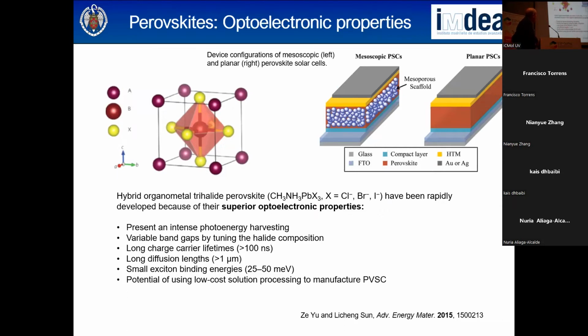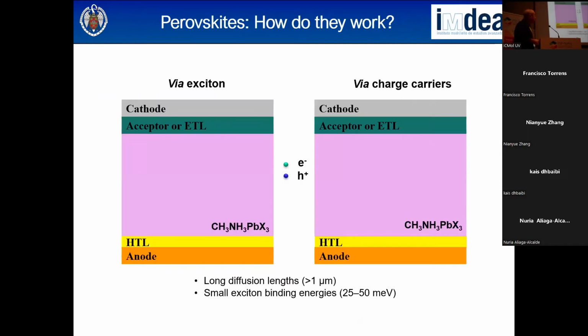Mostly, I would like to say that the charge carrier lifetime is very high, over 100 nanoseconds. The long diffusion length, over microns, and the small exciton binding energy. That is so small that when the photon creates the exciton, the separation of holes and electrons occurs very immediately. So originally, when talking about perovskites, this was the former idea of how they work: the photon forms the exciton, and the exciton has to go to the interface for separation. But that was wrong. That is typical for organic solar cells.